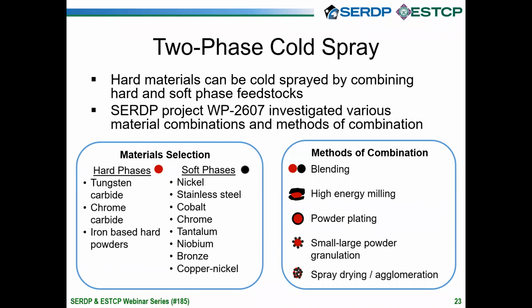So the way that we address that for this project is by using two-phase cold spray, in which we combined hard phase materials like ceramics with softer phase feedstocks. And the reason we do that is because we need the hard phase material to increase the bulk hardness of our deposit. And we need the soft phase material to give us the plasticity we need to successfully build a dense coating.